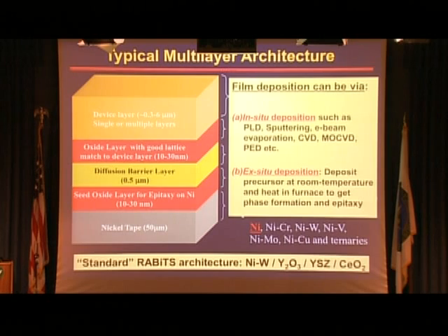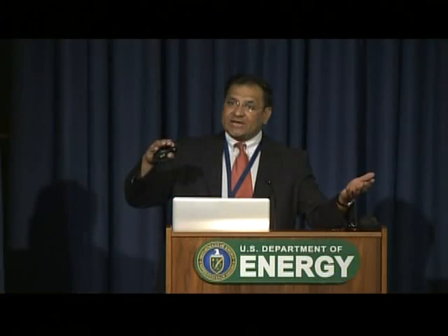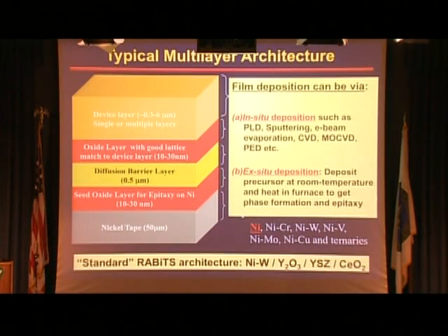Now, we can deposit these layers in 2 ways. We can either take this metal sheet, take it to a high temperature, and as we deposit, the atoms actually line up in the right configuration. That's called in situ deposition. Or we can take this metal tape, dip it in a chemical solution, it could be water-based or oil-based, and then we can put it in the furnace, and during the heating process, the atoms line up. And that's called ex situ. And we can do either of these.